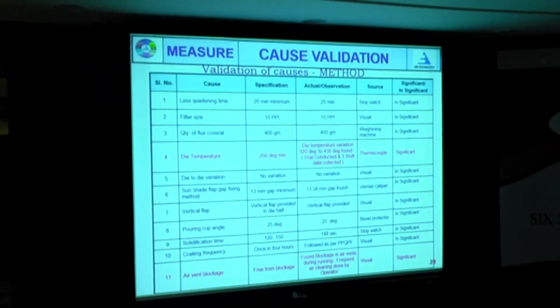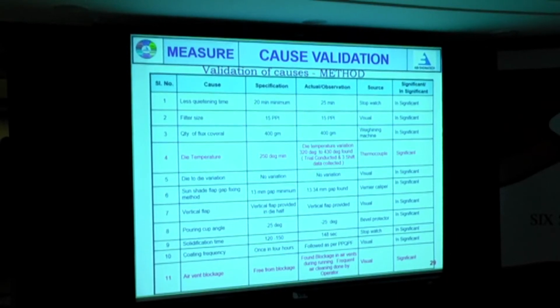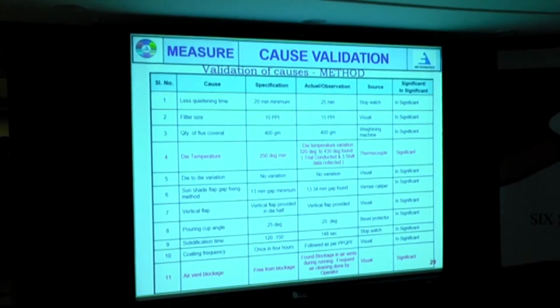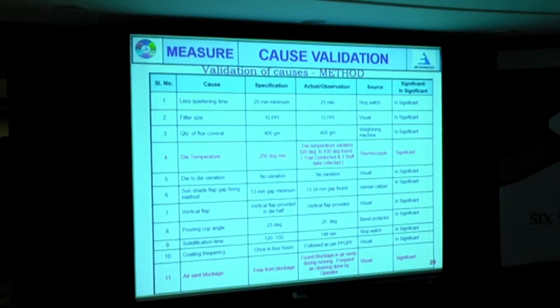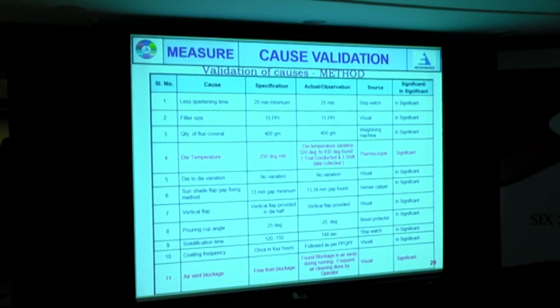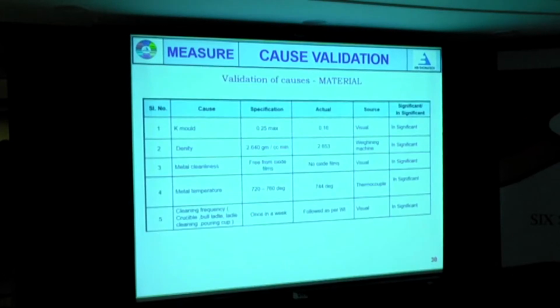One of the causes is die temperature. Die temperature variation is too high, so a trial is conducted for three shifts and data collection is to be done. Next, air vent blockage frequently occurred and the operator frequently cleans it during running production. Next, material causes are validated, there are no significant characteristics occurred.